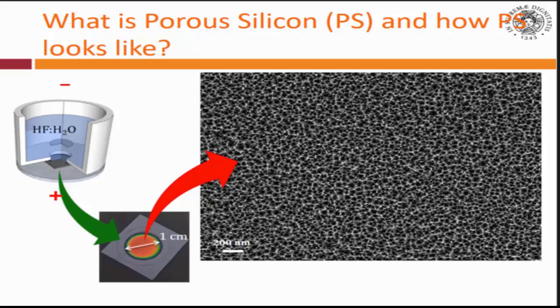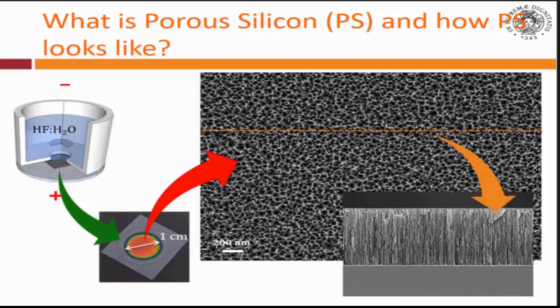The material I'm talking about today is a mesoscale material, where the pores are in the range of 50 to 100 nanometers. If you take a cross-section of this material, you can see the pores are straight, almost cylindrical, and the diameter of the pore is almost constant with depth. The nice thing is that if you interrogate the material with visible light, the wavelength is long enough to see the material as homogeneous.